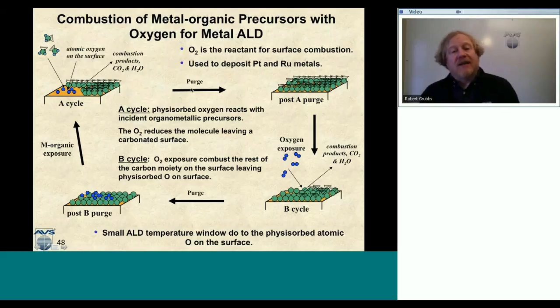And so now I've got this, it'll bond with part of the molecule onto the surface. So now I've got this organometallic surface here that's inert, and I guess I should back up and say that we use this to deposit platinum and ruthenium metals. Now remember, these metals don't necessarily form good oxides. So we're able to keep that oxygen on the surface without making an oxide bond. It just sort of sits on the surface. I should have mentioned that earlier.